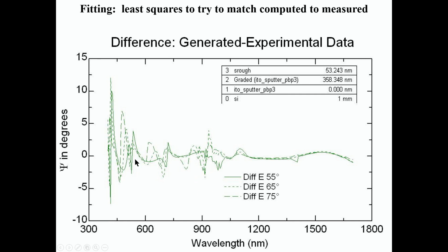This is 0, and you can see that it's close to 0, but the measurement accuracy of psi of the instrument is in a few hundredths of a degree in that order. And we are way, way beyond that. I mean, we're 10 degrees off here at certain wavelengths, and we're way, way out of the accuracy that's in the data. So this is not a good fit.